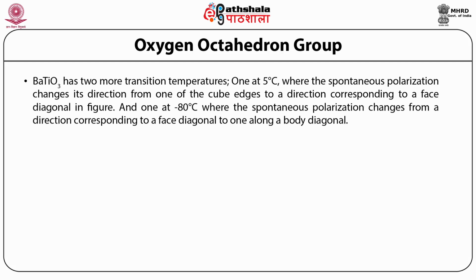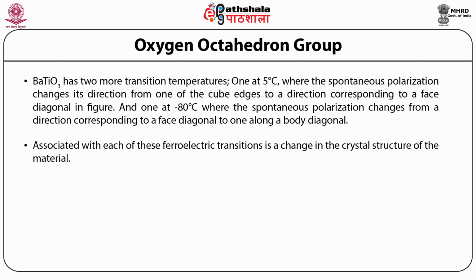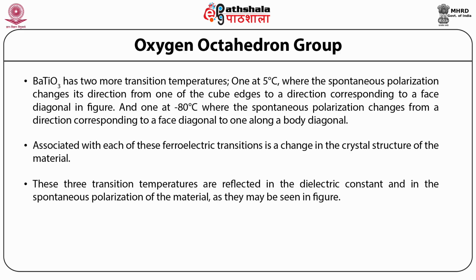BaTiO3 has two more transition temperatures, one at 5 degrees centigrade, where the spontaneous polarization changes its direction from one of the cube edges to a direction corresponding to a face diagonal in the figure, and one at minus 80 degrees centigrade, where the spontaneous polarization changes from a face diagonal direction to one along a body diagonal. Associated with each of these ferroelectric transitions is a change in the crystal structure of the material. These three transition temperatures are reflected in the dielectric constant and in the spontaneous polarization of the material, as may be seen in the figure.